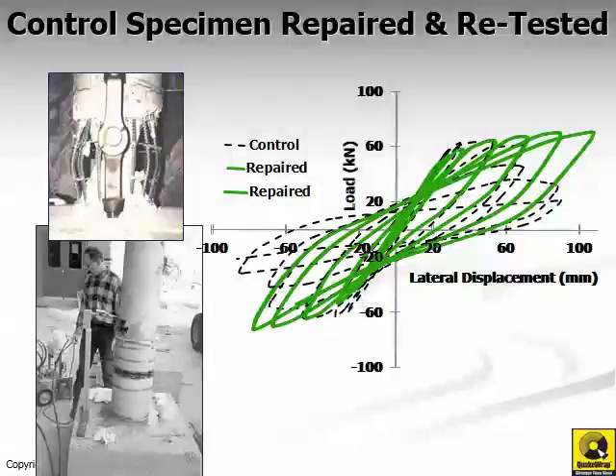And then we retested that column. Now the graph shown in green shows that already failed column being tested the second time. And you notice that we have a very full hysteretic response with very little sign of pinching or loss of stiffness. And in fact, the column continues to take more and more load as we push it further and further. And as a way of comparison, the black dashed line is the response of the original first time that this same column was tested. So clearly we have enhanced the behavior of this column.